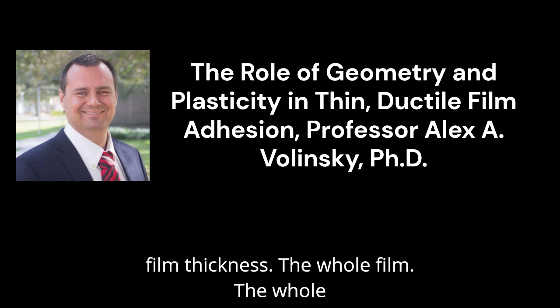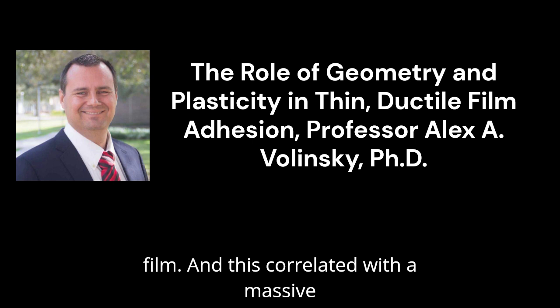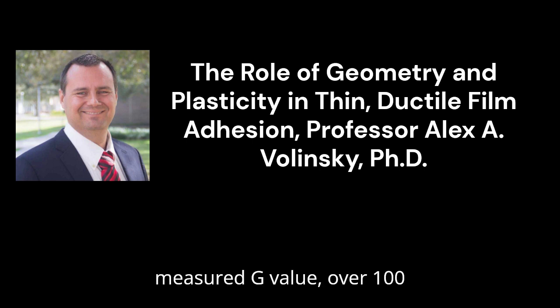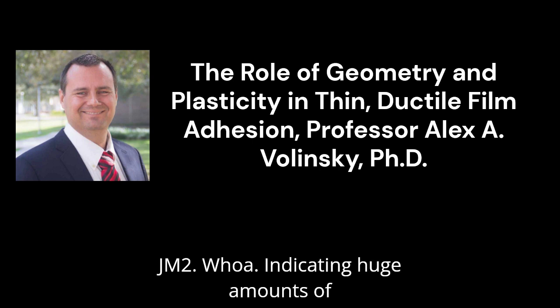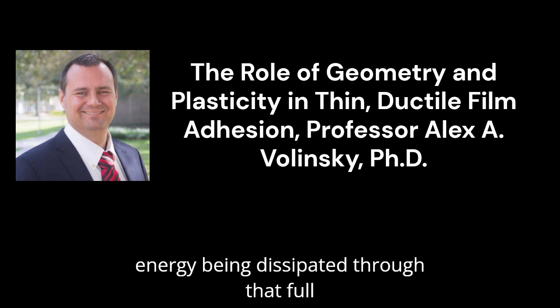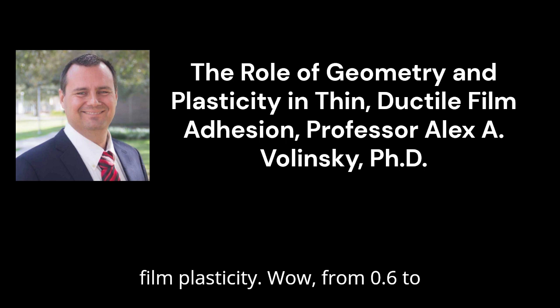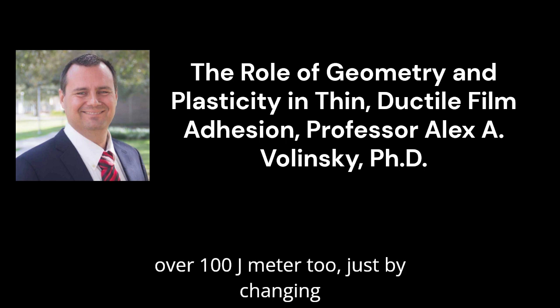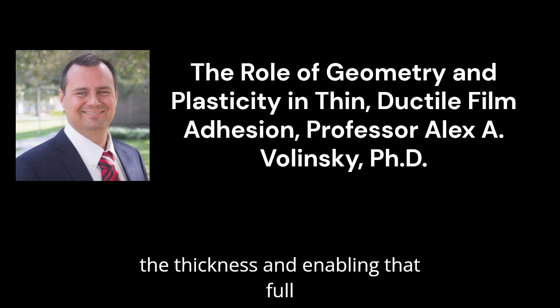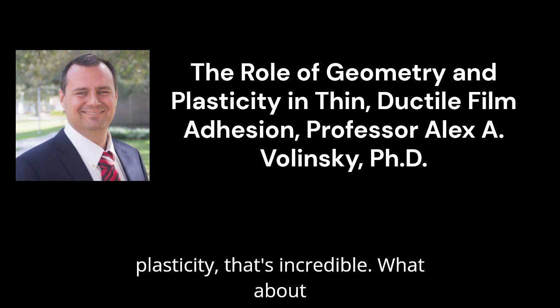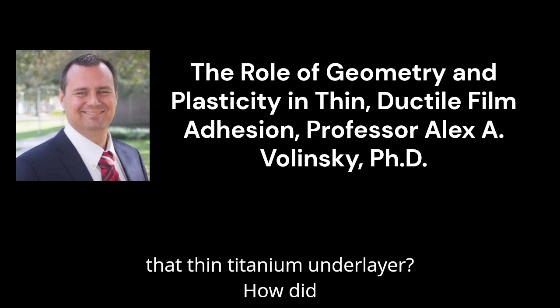The whole film. The whole film. And this correlated with a massive measured G value, over 100 J/m². Whoa. Indicating huge amounts of energy being dissipated through that full film plasticity. Wow, from 0.6 to over 100 J/m², just by changing the thickness and enabling that full plasticity. That's incredible. What about that thin titanium underlayer?